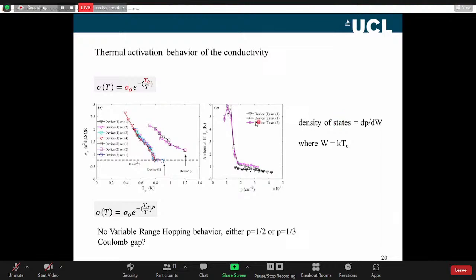And there are two things that come out of this. It must mean that in this region here, around 1.6 times 10^11, we have a gap in the density of states. So this inverse gradient is really a measure of the density of states. At high carrier densities we have a high density of states, and then it is almost a gap in the density of states.